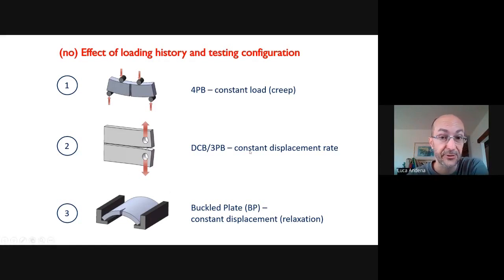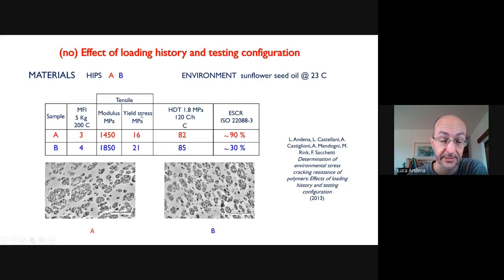And I will present you some results relating to a comparison between three different loading configurations: 4-point bending under creep, DCB, or 3-point bending under constant displacement rate, as you would do in a tensile experiment, or the buckled plate, which works in relaxation. In this particular work, two materials were selected, and it's interesting. They were two HIPS with rubber particles to toughen the polystyrene. One was a conventional grade, with slightly better mechanical properties. The other one is a specifically tailored environmentally resistant grade. Here the environment is sunflower seed oil, whose properties are slightly worse in air, but it performs better in oil.